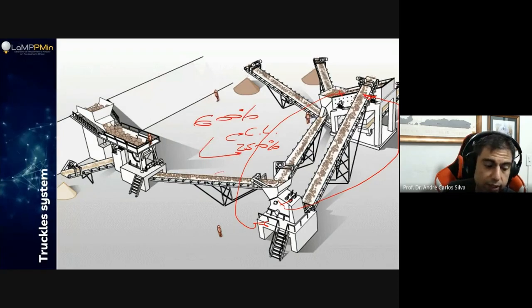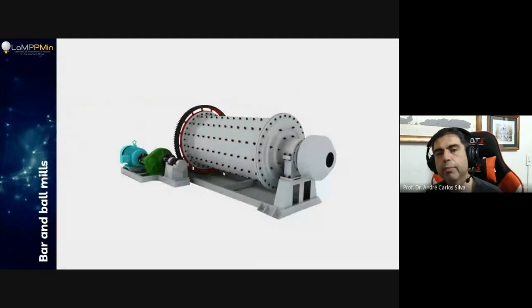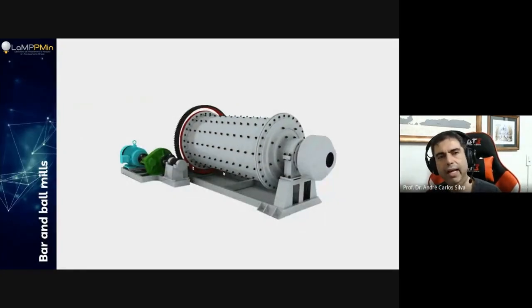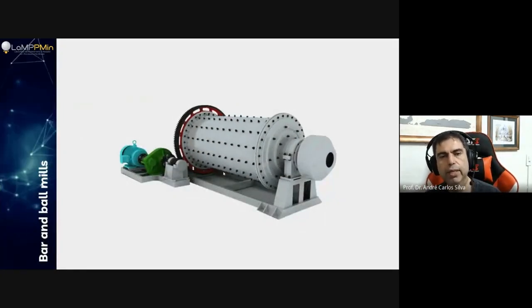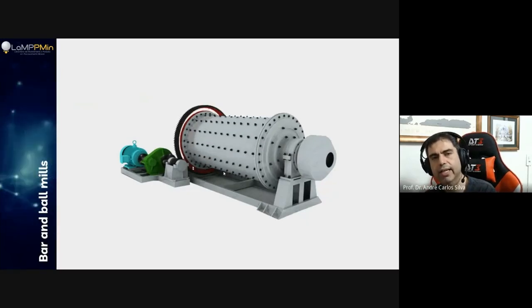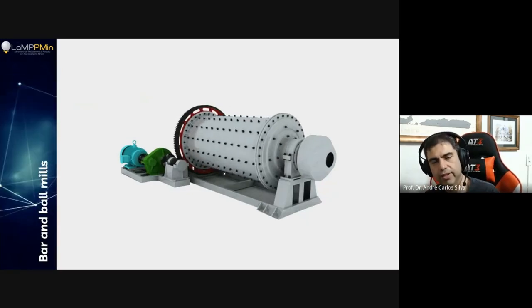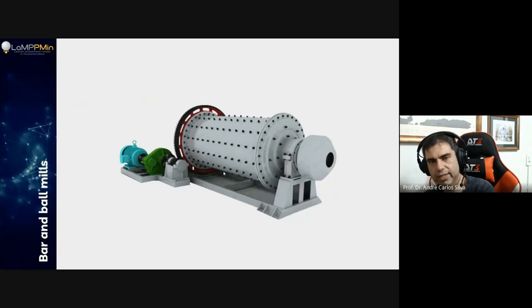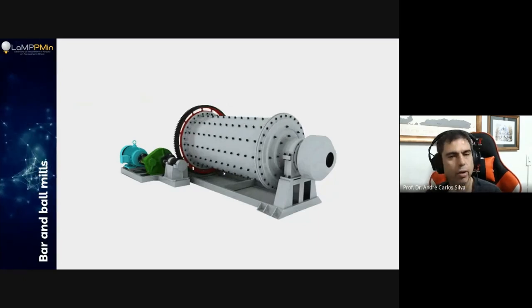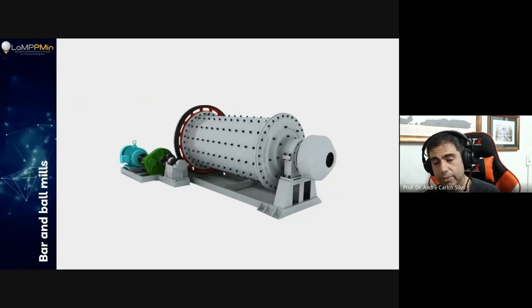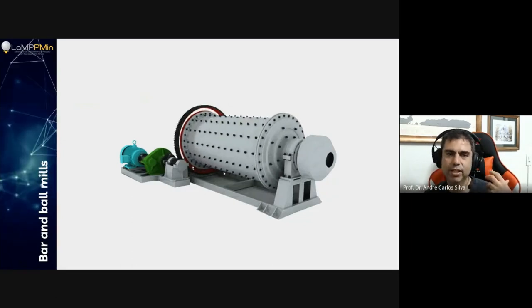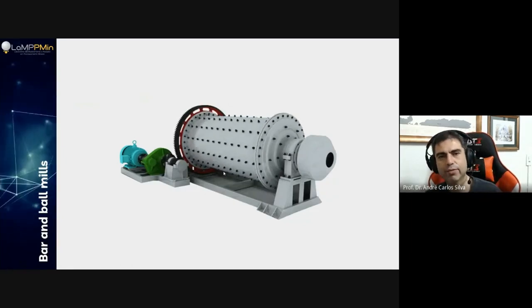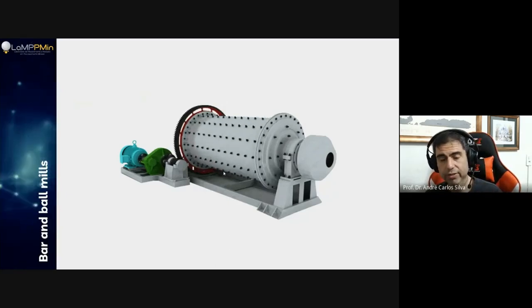Why? To avoid breaking more of our material than we actually need, okay? So we can have something called under breakage of the material and over breakage, okay? And we don't want to have over breakage, because if you have over breakage, then you spend more energy than you should, and then you're going to have a lot of slimes, and these slimes for us are just garbage. So I'm going to have to throw them away, okay?